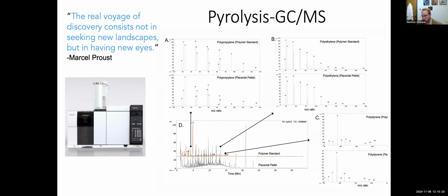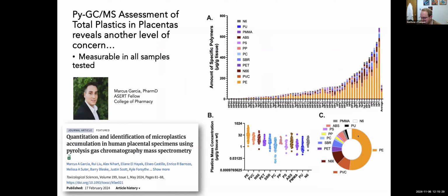And I like this quote from Marcel Proust, that we're now really looking at this problem with a fundamentally different tool. It's giving us really new insights. The first paper we published on this was Marcus Garcia's, really his first paper as a postdoc, showing that we could identify plastics of different polymers in every human placental sample we looked at. There were 62 placental samples. By and large, the average was low, around 100 micrograms per gram. But there were a lot of subjects for whom the values were 6-7 times that much.